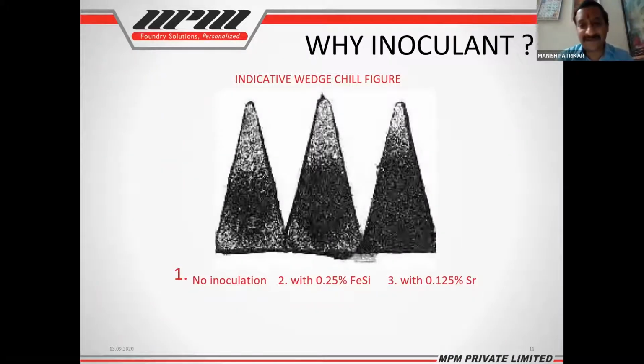If you see the first, second, third, these are the wedge chill tests. In the first, there is no inoculation. Second with 0.25 ferrosilicon, third with 0.125 strontium. So these are the elemental effects. I have not used anybody's product here because this is a technical forum. So I am trying to give the elemental effect.